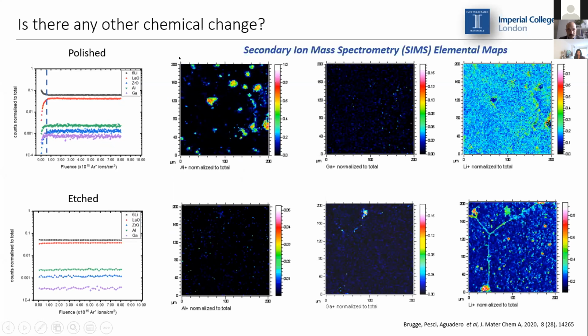And as you can see, if we compare the SIMS elemental map of aluminium, gallium, and lithium, for instance, of a polished sample, we see that we've got a segregation, especially of aluminium at the surface of the sample. And this is attributed to aluminium sitting at the grain boundaries and at pores that we've got on the surface. However, undergoing a thermal treatment, we see that the aluminium in the etched sample is much more homogeneously distributed, and we still do have a small segregation of gallium and lithium.